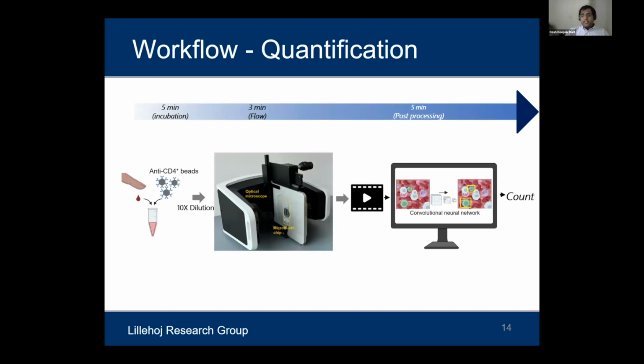So the workflow for quantification is that we do a finger prick, we take blood, we dilute the blood, we incubate it with anti-CD4 positive beads, and then we dilute the sample to 10x. We feed 20 microliters of the sample. The volume need not be precise, but it has to be close to 20 microliters. It is fed into the chip and, in a slug format, it would fall inside the microfluidic chip which we fabricated. It is placed in a way that the microscope can record a video of samples flowing through, and the camera inbuilt in the microscope would take a video at 15 frames per second, which we would post-process using the convolutional neural network, which will give us the count.